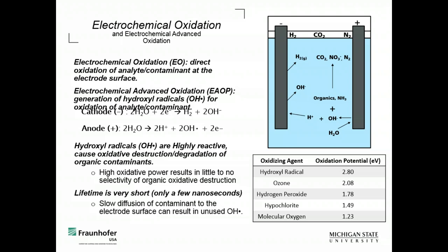But again, I talked about hydroxyl radicals a little bit, but there's some ambiguity in the literature as to whether you need hydroxyl radicals or not. But nonetheless, the hydroxyl radical is the most powerful oxidant that one can generate compared to even ozone, bleach, hydrogen peroxide, things like that. But again, we don't always have to use hydroxyl radicals. But nonetheless, it's crucial that anything we're trying to oxidize gets very, very close to the electrode surface. I'm talking nanometer, maybe sub-nanometer distances from the electrode surface. Because even if we're generating a hydroxyl radical, these are so reactive that the lifetime is a few nanoseconds. So you've got to get these to the electrode surface in order to actually have something occur. And I'll talk about that.